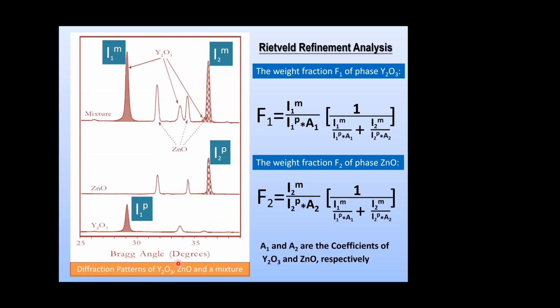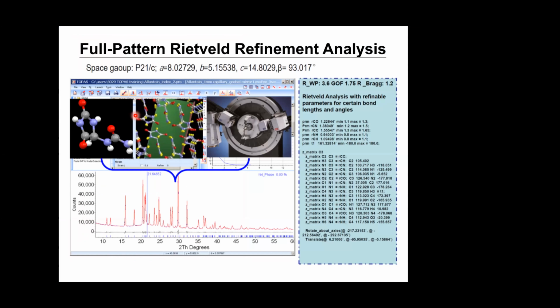The key is what we call Rietveld refinement analysis. Basically, you take the profile, the shape of your peaks, and you use theoretical calculation to simulate the peak heights and peak shape, which means the width of the peaks, for example, and you try to match it to the standard one. Then you start to know, in terms of quantity, the amounts of the different crystal phases there.